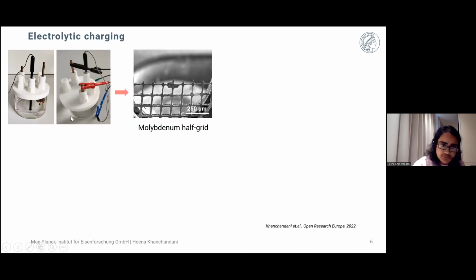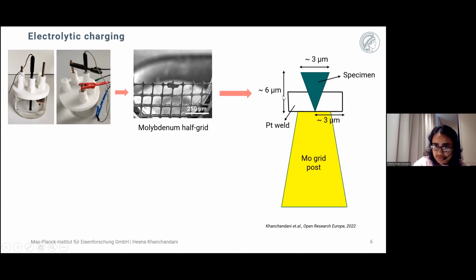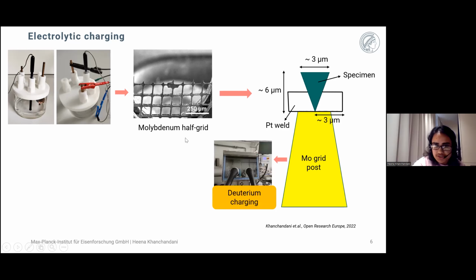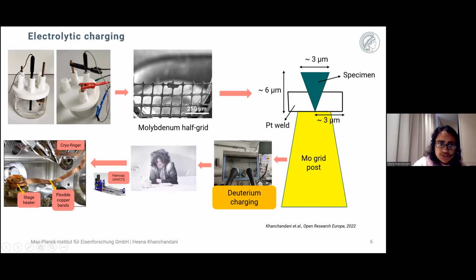For this, the conventional atom probe geometry of the silicon coupon mounted on a copper strip cannot be used, because the copper clip will go into the solution and will react with the charging solution. So molybdenum half grids, which are typically used for TEM specimens, were used for mounting these specimens. These grids were then mounted on grid holders, which were connected to the cryogenic puck, which was immersed in the solution. For this, we also prepared thick platinum-coated wedges of the sample on the molybdenum grid, because the samples which are sharpened to the APT specimens would also dissolve into the solution. We first prepared the thick platinum-coated wedges, which were charged in this electrolytic cell in a glove box with deuterium. They were then quenched in the glove box, and transferred via a pre-cooled suitcase to the FIB, which is equipped with a cryogenic stage, to mill these specimens into atom probe specimens for further analysis at cryogenic temperatures.